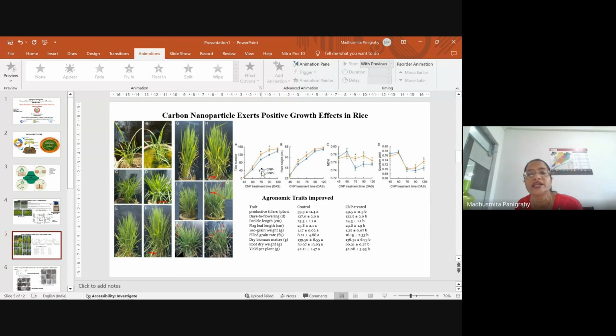We gave the carbon nanoparticle in 4 doses at 15-day intervals, and we took different morphological parameters, and we have seen that the tiller number, the plant height, the chlorophyll measurement, and the quantum yield of photosynthesis increased after CNP, carbon nanoparticle, treatment.